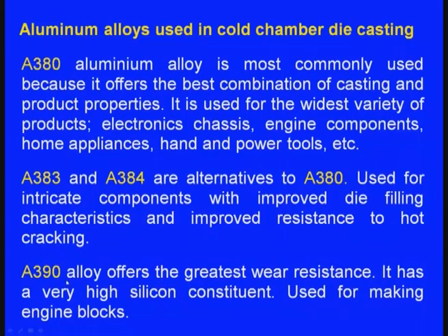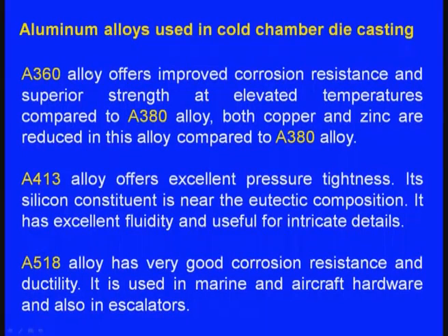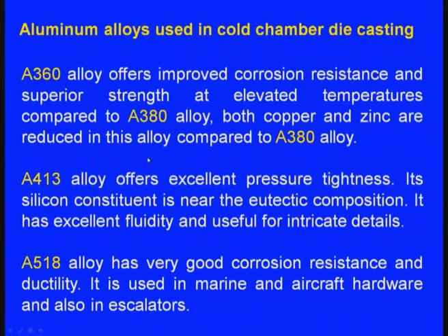Next one, A390 alloy offers the greatest wear resistance. It has a very high silicon constituent, used for making engine blocks. Once there is a high silicon proportion, what happens? It enhances the fluidity and also induces wear resistance to the cast product. Next one, A360 alloy offers improved corrosion resistance and superior strength at elevated temperatures compared to A380 alloy. Both copper and zinc are reduced in this alloy compared to A380 alloy.